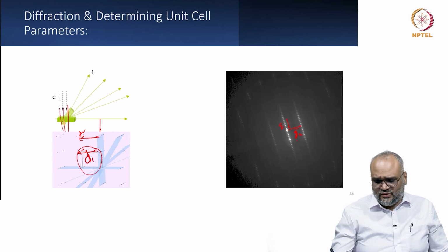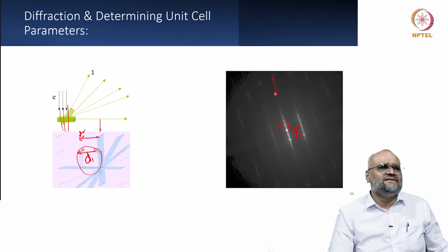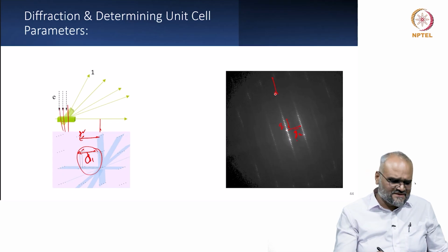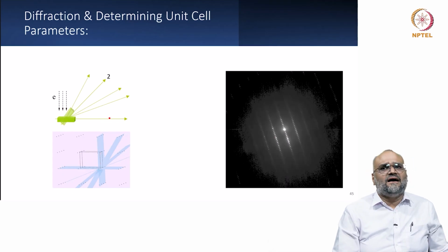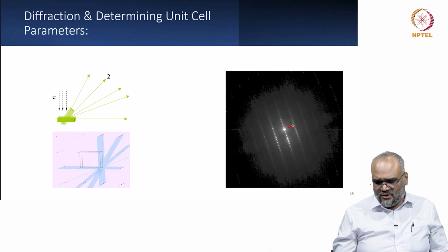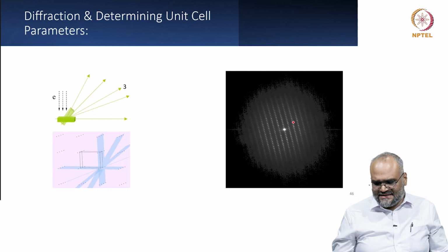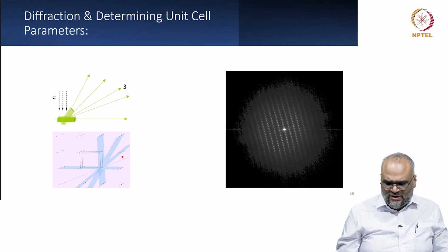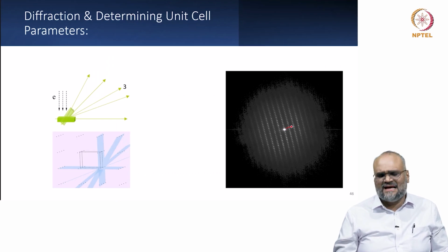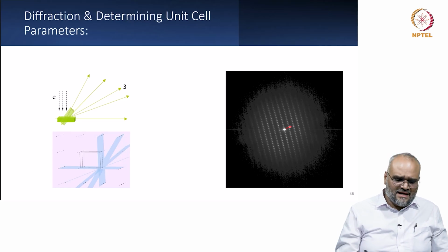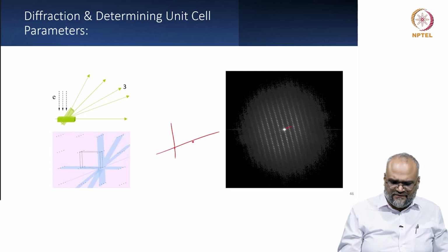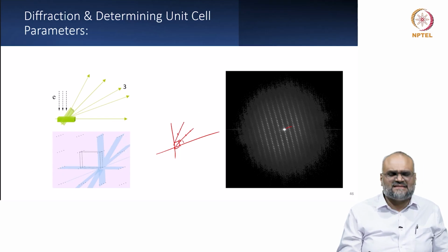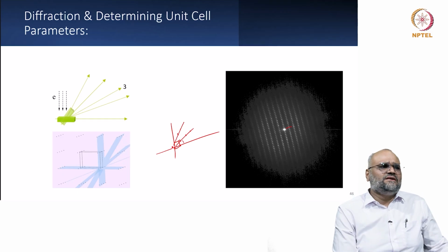If I now use one of the crystallographic axes as constant and I now tilt the specimen in this direction, I obtain the planes with varying G1 and this G2 remains constant, and with these variations, whatever projections I record, I can overlay them over each other and measure them and plot them on a kind of graph paper and see with how much angle of deviation these diffraction spots are changing, and I can construct the projection of a reciprocal unit cell.